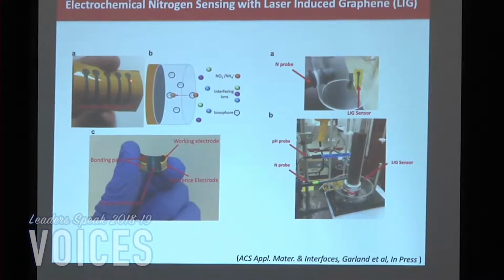So I mentioned too that we were working with fertilizer ion detection, and this is a little bit different type of graphene. This is called laser scribed graphene. We take Kapton tape, which is polyimide, and we're able to convert that structure of carbon from sp3 to sp2 hybridized carbon, which is what's found in graphene, just by treating it with a laser, much like the laser that I'd mentioned before. That burns or chars, or really changes, the carbon into that structure that's conductive.